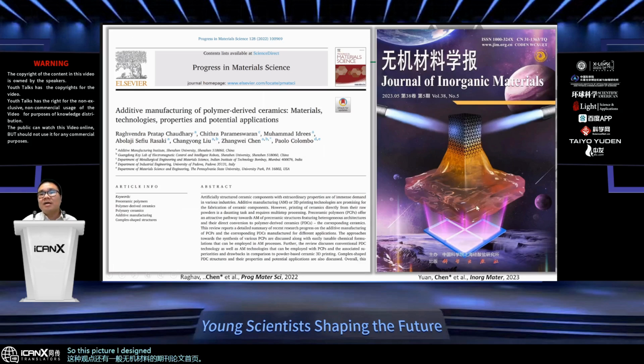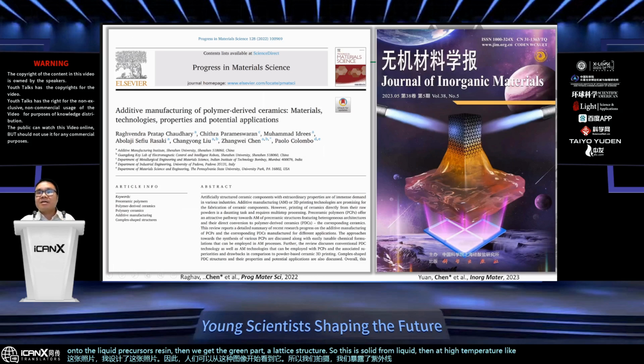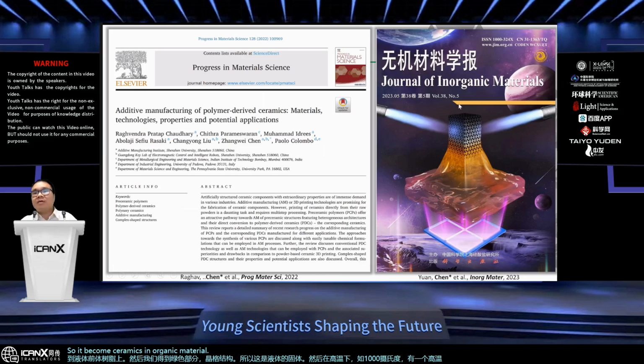So this picture, I designed this one. So it's very visible that people can understand starting from this kind of image. We expose our UV light onto the liquid precursor resin. Then we get the green part, a lattice structure. So this is solid from liquid. Then at high temperature, like 1000 degrees C, there's high temperature pyrolysis. So it becomes ceramic, inorganic material. And we have a larger background in aerospace, so there will be microwave protection and high temperature protection for this specific composition of the ceramic material.